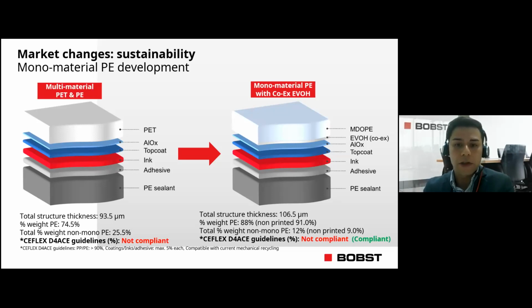If we look below the structures, there are some data on the total laminate structure by thickness and weight. We wanted to show the percentage of weight of non-monomaterials versus the total structure. The structure on the left, as we have already established, is non-compliant due to its mixed material nature. The structure on the right is partially compliant with the CEFLEX guidelines, as a percentage of non-mono PE is within the ballpark figures that is either compliant or non-compliant. Of course, one can design for compliance by changing the layer density, for instance, increasing the PE sealant thickness.